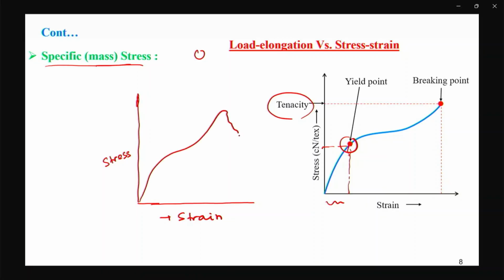So, this is one breaking pattern, where the breakage does not take place at the peak value, unlike the earlier one. This is the peak point and the point here is the breakage point. The breakage point is lower than the peak value. Here fiber to fiber slippage takes place in textile material. So, this type of phenomenon happens. After reaching the peak value where the fiber to fiber slippage takes place, still there is no disintegration. Slippage takes place, and it ultimately disintegrates at the point which is lower than the peak point.